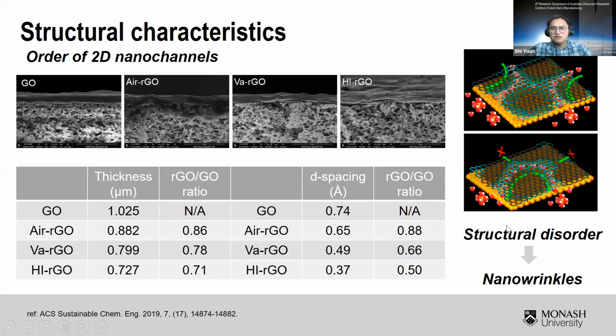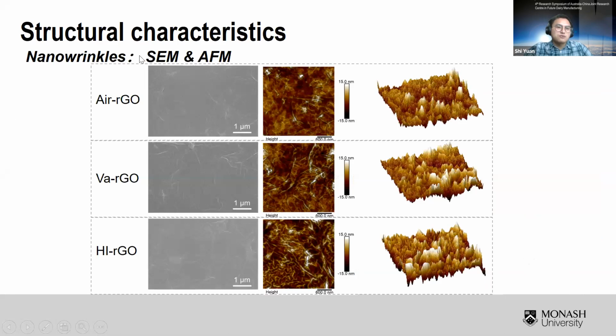So this kind of structure disorder will lead to the formation of nano wrinkles, which is the factor we think is very important. So we then directly characterize the nano wrinkles by SEM and AFM, and we can easily observe the difference in their surface structure and the density of the nano wrinkle.